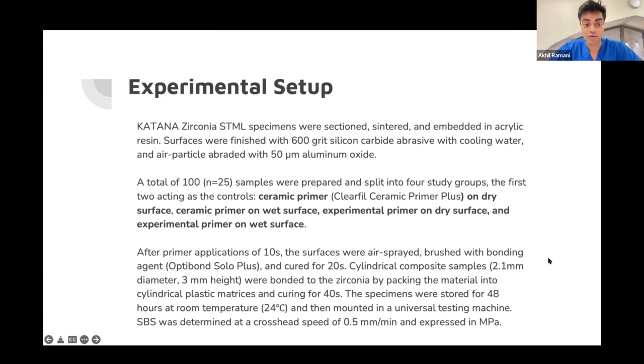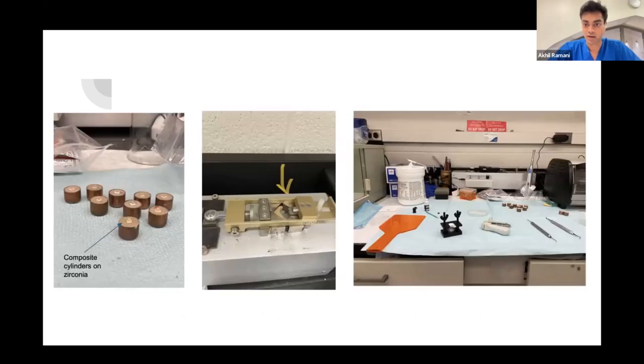After primer applications of 10 seconds, the surfaces were air sprayed, brushed with the bonding agent that we use in the clinic, which is OptiBond Solo Plus, and then it was cured for 20 seconds. So in the next picture here, I'll show you the entire setup. On the left, we have the copper cups, and that's what the zirconia is embedded into using acrylic. And then you can see there's a cylindrical section of composite that is placed on using this apparatus that we have. In the middle, that's what is used to test the shear bond strength.